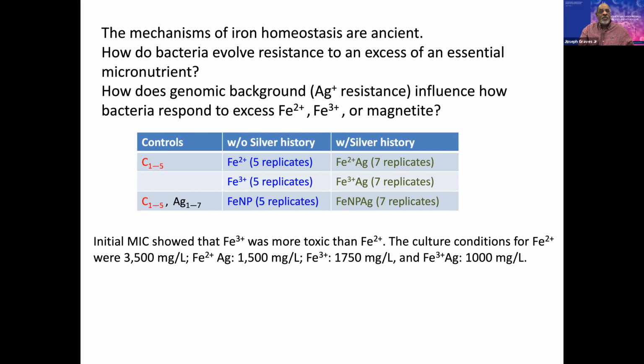Now, to do the experimental evolution to generate iron-resistant populations, in this study we're talking only about the iron 2 populations. We first determined an initial minimal inhibitory concentration. Now, to do an experimental evolution project, you obviously cannot try to grow the bacteria at their MIC. In other words, if you're at the MIC, none of them survive, none of them replicate. So you have to use a sub-MIC concentration.